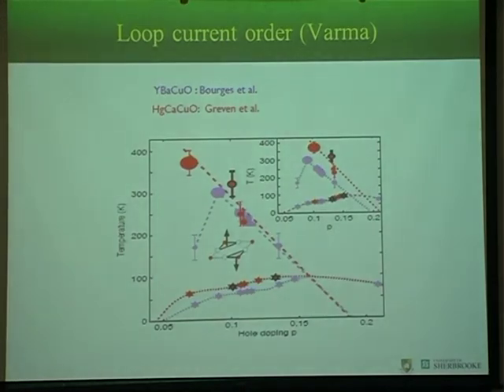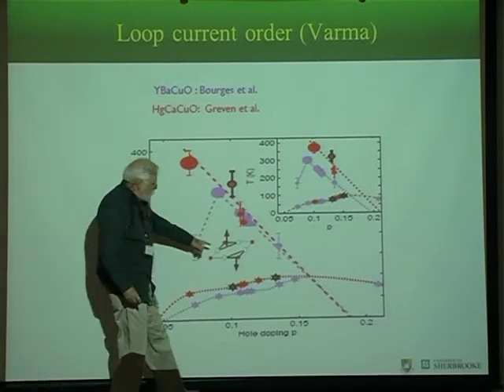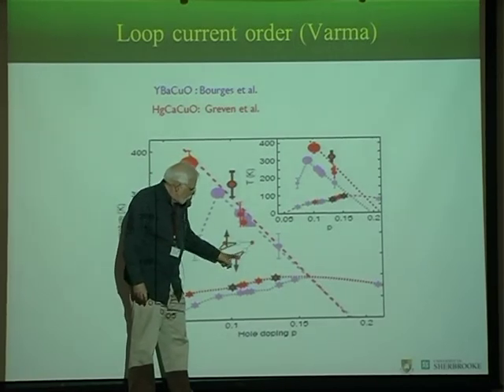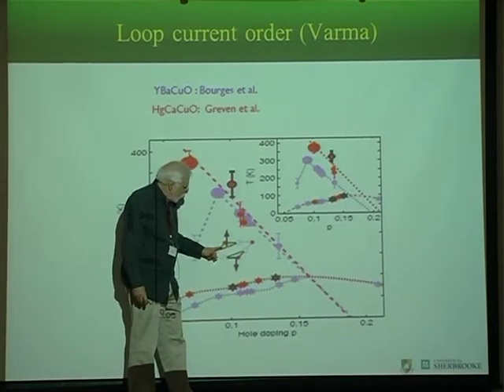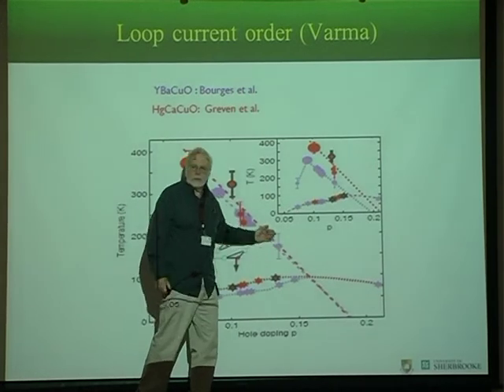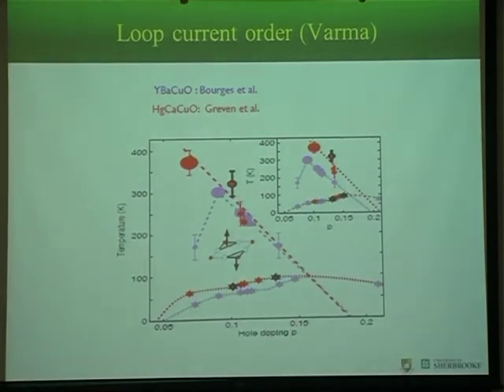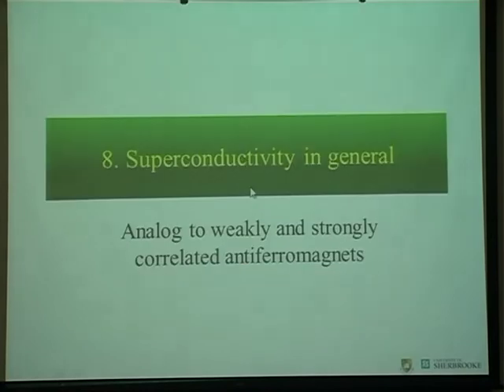And another example where one would need to take a more complicated model is to explain these experiments. In fact, the theory came first by neutron scattering, where they look at polarized neutron scattering. And they looked now not around pi, but around q equals 0. So it's translationally invariant. Yet they see an onset that looks like a phase transition. What is ordering now is within a unit cell. You see this is a unit cell. And what the theory proposes is that there are loop currents within a unit cell. And this is where the phase transition occurs. So they would like to say that the pseudogap in the whole doping range is a real phase transition. It has to do with these loop currents. If it's the case, again, the one-band Hubbard model is not appropriate. Now, some experimentalists I talked to are not convinced by these experiments. Again, these are very small signals and so on, but, well, we need more confirmation.